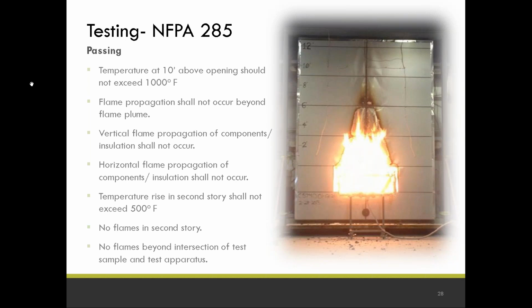Passing, there's a lot of things that have to happen to pass this test. The most important and the most common failure point is that at that thermocouple 10 foot above the top of the window, the temperature shall not exceed 1,000 degrees. And there's actually 3 thermocouples in the depth of the wall. And the one that almost always fails, if it's going to fail, is the one at the outside surface of the wall. You also can't have flame, which actually propagates beyond the flame plume. In other words, the gas has a flame plume, but the material itself can't burn past that flame plume. The flame also can't go sideways out either side.